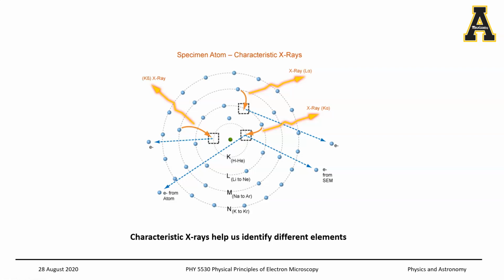So if you're able to excite or knock off the electrons from the innermost shell of these respective metals or elements, you have a signature energy transfer, so that they are replaced by electrons from the outer shell, and this is very important in the chemical identification process that is involved with electron microscopy. Okay.